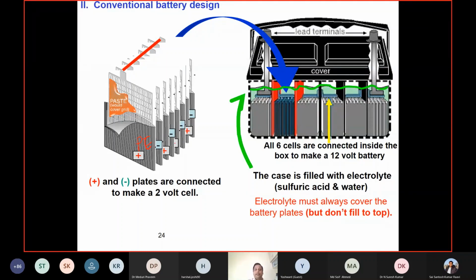Okay, so you see, this is 1, 2, 3, 4, 5, 6. So 6 compartments, 6 into 2, you'll get a minimum of 12 volt. In the full charge condition, you'll get 13.5. You use aqueous sulfuric acid. Generally, 4.5 molar sulfuric acid is used, and then the cover is put on top and sealed.